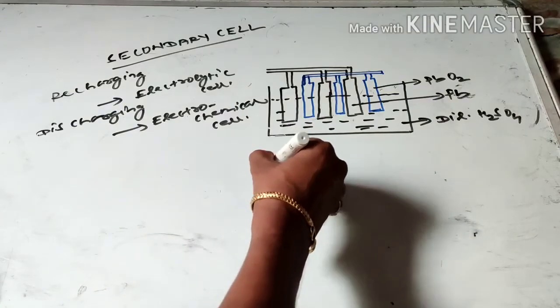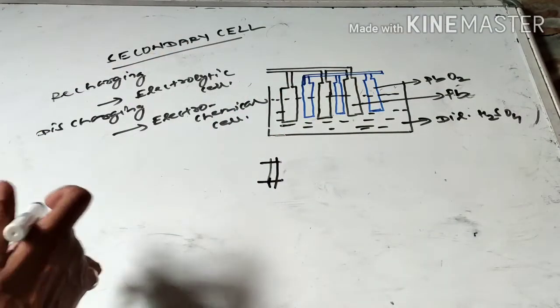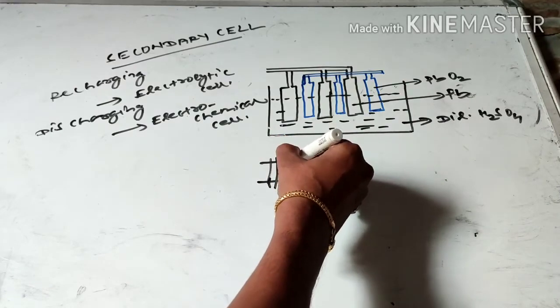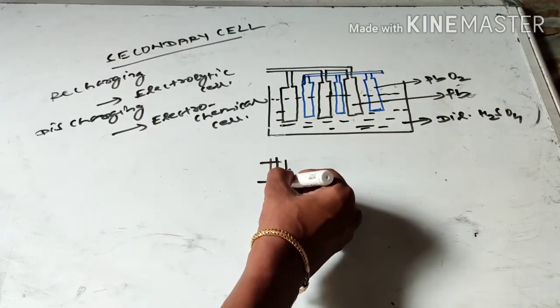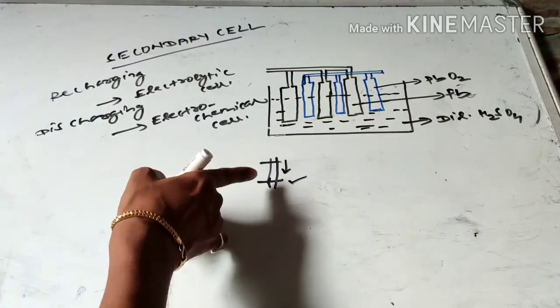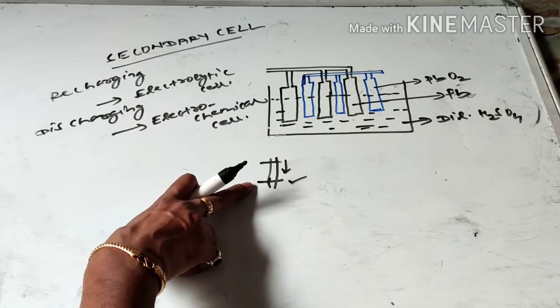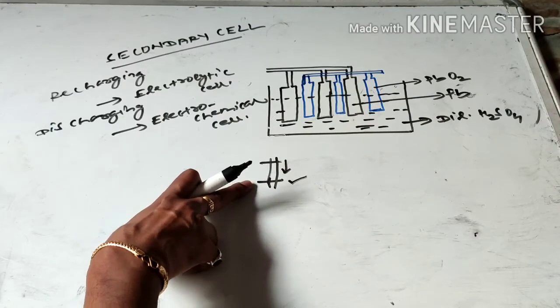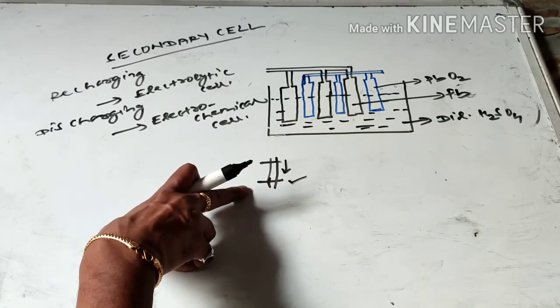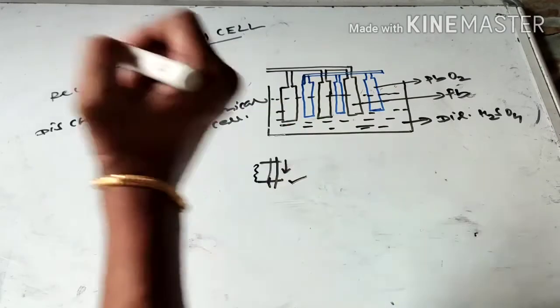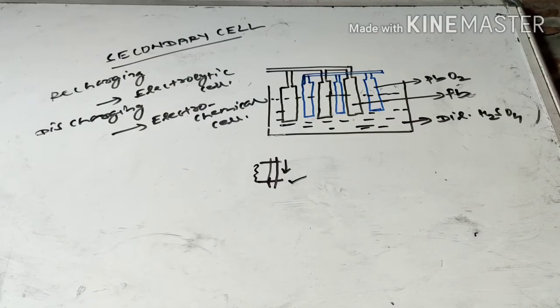If the density of sulfuric acid goes below 1.20 g/cc, the cell will be totally dead. We use a battery indicator which indicates when the sulfuric acid density starts to decrease. Inside the battery there is a marker — when the battery starts to discharge day by day, the level starts to decrease. When the level moves below the marker point, that indicates the density of sulfuric acid is less than 1.20 g/cc.